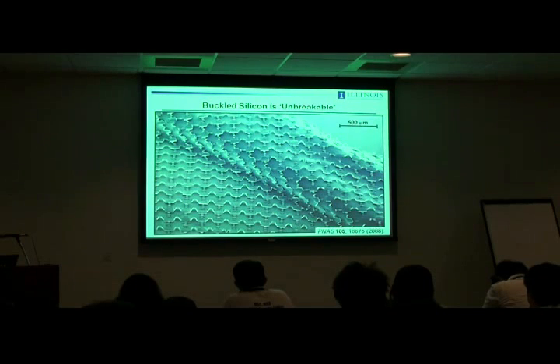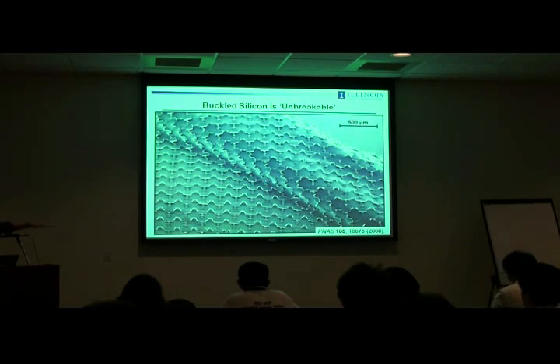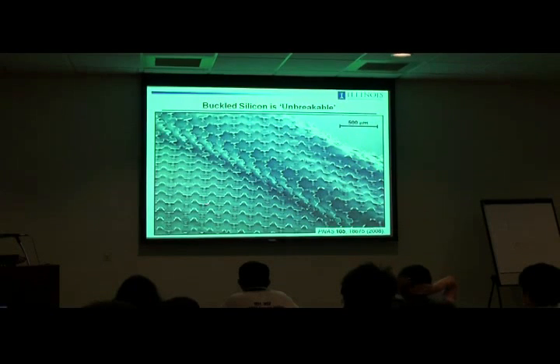And so how can you bypass those limitations, but still retain silicon and some of the simpler ideas that allowed you to get to that point? And the answer is that you do two things. One is instead of the circuit existing in a uniform sheet, you etch it into the geometry of an interconnected mesh. So in this particular case, it's just a simple illustration of the idea. It's islands connected by straight bridges. So this is a thin sheet nanomembrane of silicon, and structured into this mesh, number one. And then number two is by controlling the surface chemistry of the underlying silicone rubber, you can induce selective bonding of the silicon only to these island regions.